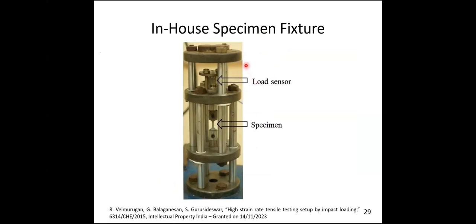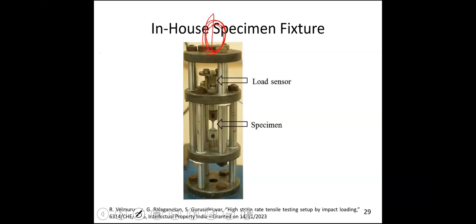This is the picture of the setup which we designed to do the high strain testing. For example, you can observe my laser pointer. When the drop mass hits the fixture at this point, the sample will fail in the tensile mode. Maybe I can show with the pen. When the mass hits this place, the sample will try to fail in a tensile mode. This is the principle behind this. So just by dropping the mass, it is possible for us to apply the high strain rate loading to the composite sample. This is what I wanted to convey.